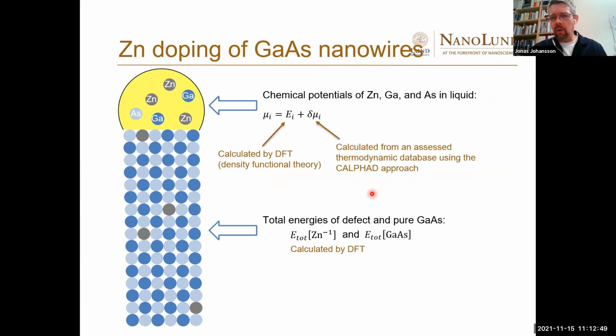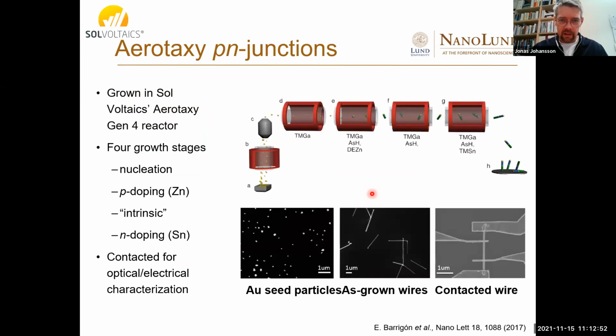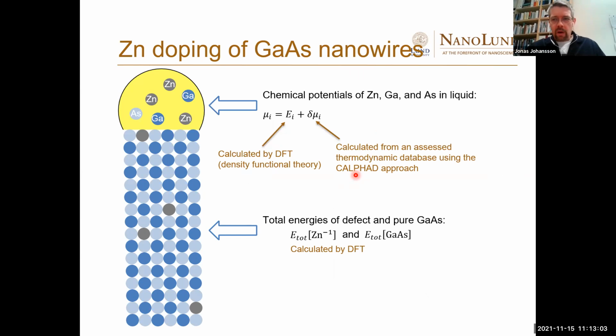So now I would like to move forward to take a little look at the p-doping of aerotaxy reactors using diethyl zinc. So the model system is as follows. We have a liquid gold-based alloy here containing arsenic, gallium, zinc, and the rest is gold. Here we have the wire, the gallium arsenide wire, and we have some zinc atoms on gallium sites. Zinc prefers to take the gallium sites, and then it will be p-doping.